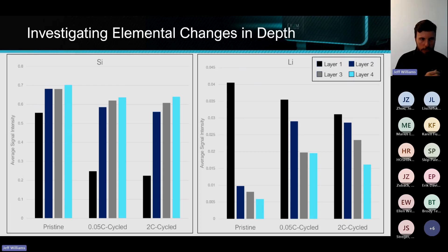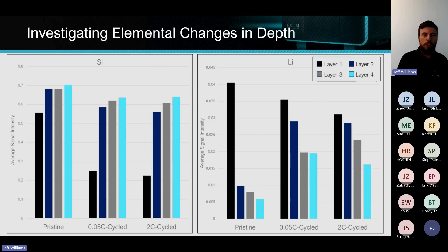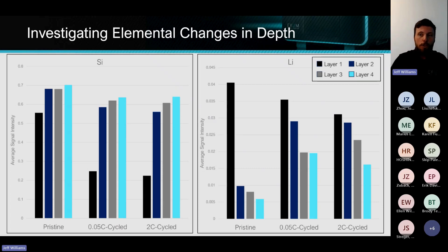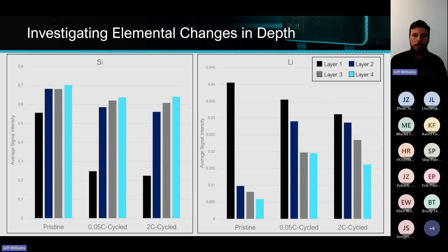This is average raw signal intensity. On the pristine anode, we have higher silicon actually in the first layers, and then it's relatively homogenous going down. As we start cycling, we actually start to lose some of that silicon in the first layer, presumably because it's being displaced during charging — so we're looking at that interface. And we see a huge spike in lithium in the pristine sample, which should have very low lithium. This was the first red flag for process control.